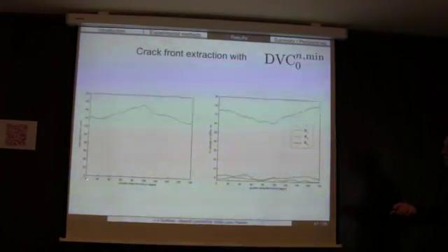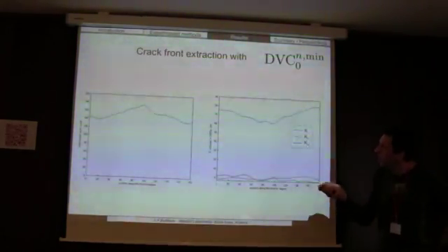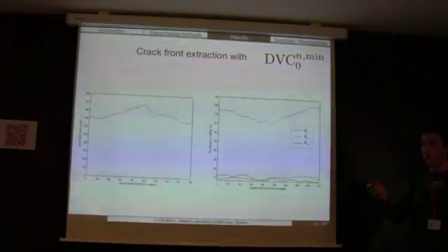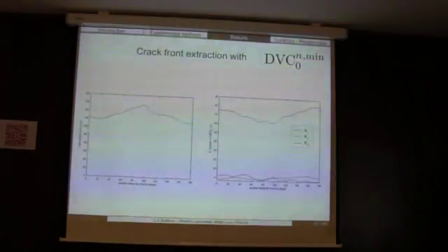So 0 means at the surface, 180 is also at the surface, and 90 is in the bulk. You see that we get a crack which is small. It's 150 microns, more or less. So it's a small crack. We get values which are not really reasonable. It's almost 0 for K2 and K3. But for K1, if you do it like this, you find something like 70, which is, of course, physically meaningless.